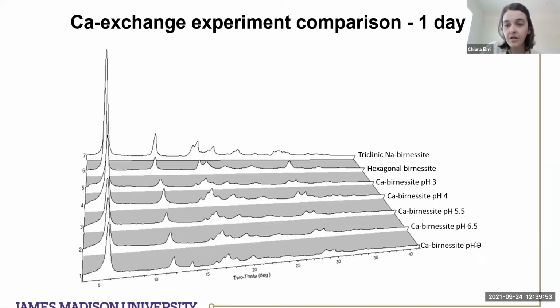In the calcium Birnessite at pH 9, you also see this extra peak. This is the calcite. It shouldn't be there, but it was synthesized because of the reaction of the CO2 with the solution, and there was a precipitation of calcium carbonate during this exchange that didn't happen at the lower pH.